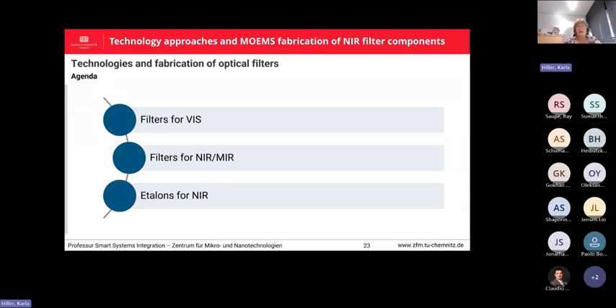But as I have shown at the beginning, the filter needs more elements. So we have to integrate the electrodes. We have to establish the optical gap. And that's why for the complete filters, in the visible range, we have still used the Bragg reflector layers. So I will show this approach a little bit more in detail, and then come back to the near infrared or mid infrared filters using the silicon reflector carriers.